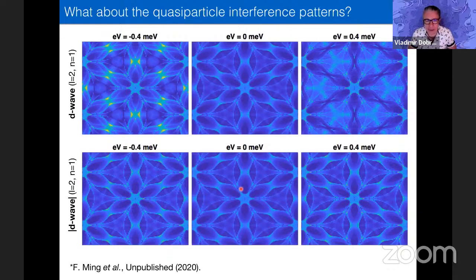But it turns out that when you self-consistently calculate the renormalization of the quasiparticles, there's an induced potential that's actually created by interactions around the impurity. And that can actually suppress the perturbation that the impurity creates in the electron gas to some modest region. If you just do single site DMFT in real space, a version of which is the Gutzwiller type of calculation, which you can also do in the superconducting phase, then you find that, for example, a superconducting order parameter will be affected by the impurity, but only very close to the impurity, as opposed to getting these long tails, which you would expect, for example, if you have d-wave nodes and so forth.